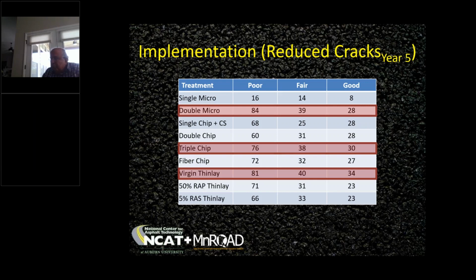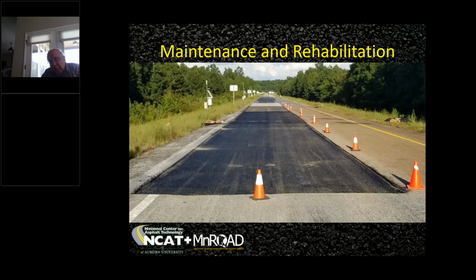And you see very similar performance between a virgin thin lay, a triple chip seal, and a double layer microsurface. That gives you some information if you're an agency or an owner: what are my options, and what kind of life cycle performance do I expect to get, so that you're not comparing a single layer microsurface to a thin lay, because you're going to get significantly better performance from the thin lay compared to the single micro, but very similar performance from a double micro compared to a thin lay. So cities and counties and state agencies can factor in their life cycle costs based on these curves that we're generating from this experiment.